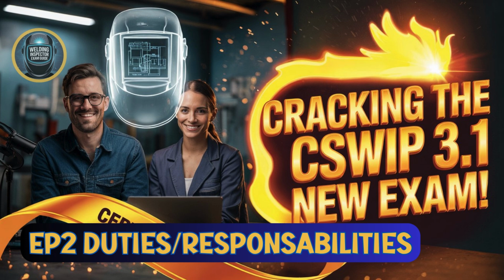Absolutely. And they oversee things like post-weld heat treatment, or PWHT, heating the whole thing up after welding to relieve stress. They check the furnace charts to make sure it was done correctly. Same for any pressure tests or load tests, monitor them. Check the records. So overseeing all the final checks and tests, not just looking at the weld surface. Exactly. And all of this culminates in perhaps the least exciting but most critical part, documentation.